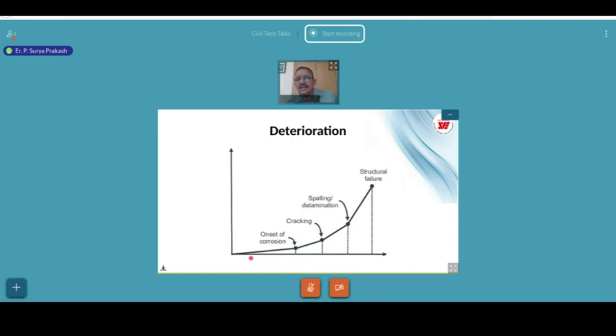So here we can see, if we have a 50 years of life, maybe about 20 years you don't see any much problems if all is done well. But after 20 years, you have to check once for the onset of corrosion in the rebars. So we have these non-destructive testing methods. I have seen many buildings which are dismantled within 20 years also. We have seen the dismantled structure, we have seen the corroded reinforcement, and the concrete quality being also very bad. Concrete also has deterioration, and the cracking starts once the onset of corrosion happens, and the spalling, delamination of the cover portion we see within 30 to 40 years, and the structural failure happens after that.